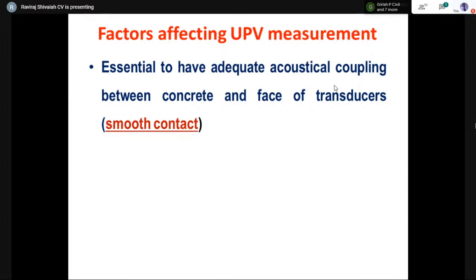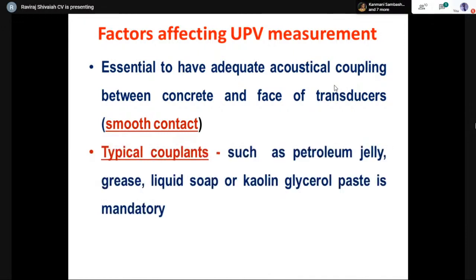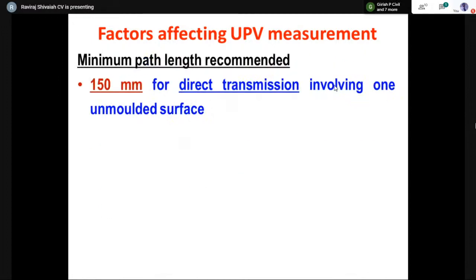But before we do this on a smooth surface, we also insist on applying couplants, such as petroleum jelly, grease, liquid soap, or kaolin glycerin paste, on the surface of concrete, and then we keep the transducers on top of it. Because please understand, the time we are trying to measure is to an accuracy of plus or minus 0.01 microseconds. So even a small void or space is not desirable in this case. There should be perfect smooth contact between the concrete and the face of the transducers.